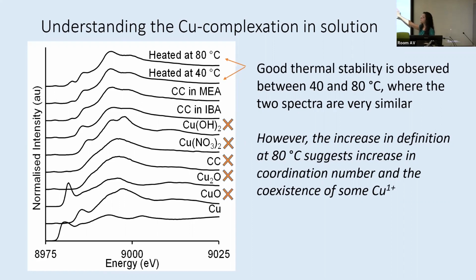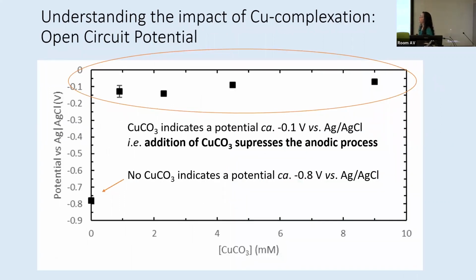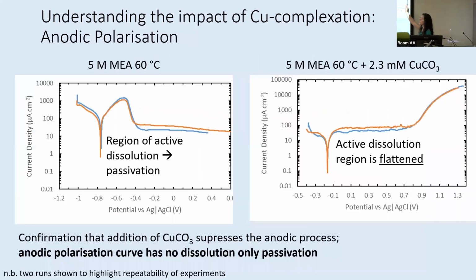And so what's happening in our system becomes something that we have to probe using electrochemistry and using quartz crystal microbalances. And so what you can see here is that the addition of copper carbonate, as I said, shifts our potential way up, and then there's very little change depending on the concentration. So it's clearly not strongly concentration driven in terms of the behavior.